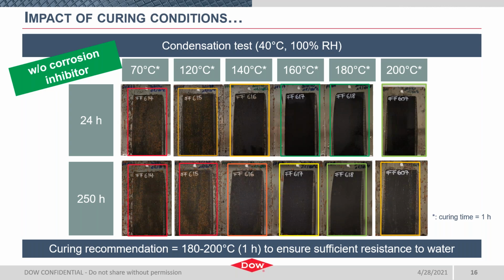Having too low of a cure temperature seems to be detrimental to the level of water resistance within these test parameters. And I think it's worth noting, it's not shown on this slide, but we have initial results indicating that a shorter cure time at 200 C actually provides a similar performance in this humidity chamber as the coating cured at 180 C for an hour. So again, although the results here are going to give us that recommendation for bake cure above 180 C, the fact that we can simply change the cure time to tweak performance gives us extra flexibility in different applications that may have an already established max cure temp that they can achieve.